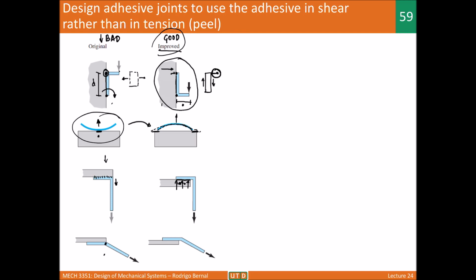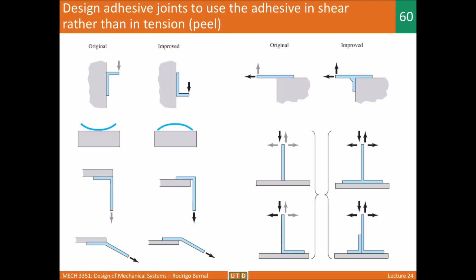Here, if you do a sum of moments, you're doing a peeling action over here. That is canceled if you use this like this, because although there is a moment over here, the reaction is pressing on the adhesive layer instead of peeling on the adhesive layer. And here there are other examples which follow the same logic, where you're trying to modify the constituents of the joint or the geometry of the whole joint such that you're using the adhesive in shear rather than in tension or peel. So this is the most important message related to adhesive joints.